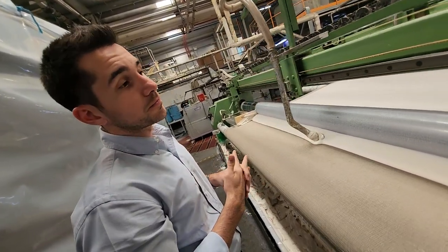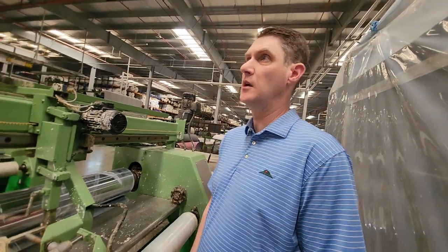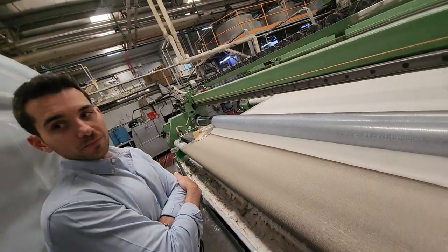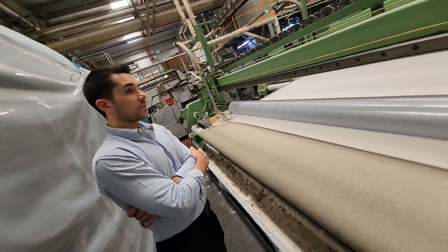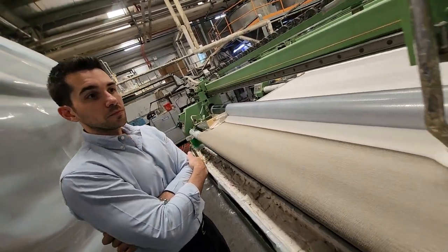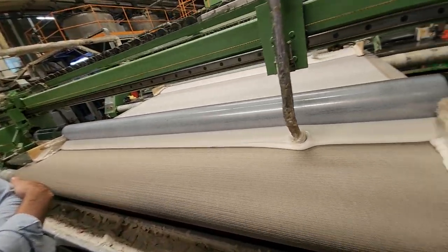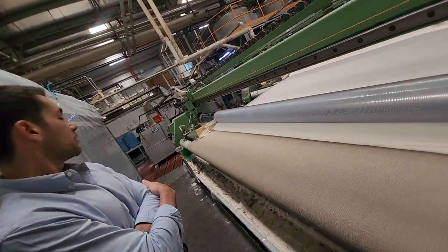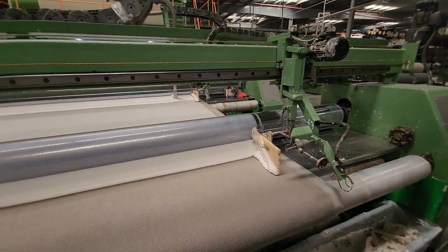The advantage of the fleece backing is flexibility, softness, and convenience for the installer — it's much lighter, cuts clean so seams are tight, works easier around corners, doesn't damage baseboards or walls, folds easily on stairs, and is much easier to handle. It's also much easier in winter — action back gets brittle and rough in cold weather, whereas fleece handles much better. And because there's no filler, delamination performance is actually better — with filler you get less dimensional stability.